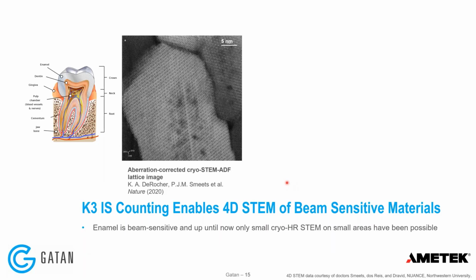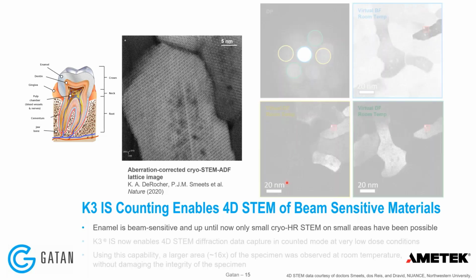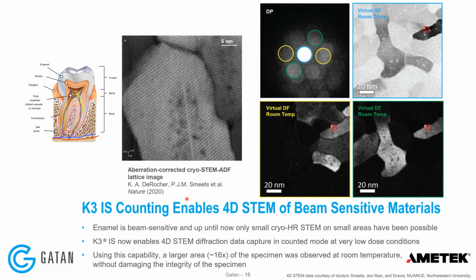Here is a nice example from the K3 IS camera from Northwestern University, again using virtual imaging. They are looking at teeth enamel. This is a very beam sensitive sample, and with the K3 IS they can do electron counting. They were able to do 4D STEM at much lower doses than they used to before. What that gave them was twofold. One, being able to prevent the specimen from being damaged by going to lower doses. And because the dose was low enough, they didn't even need to freeze the sample and go to cryo conditions to image the specimen. So before the K3 IS, because they couldn't do electron counting, they had to go to high doses, and that required a cryo specimen to prevent beam damage.